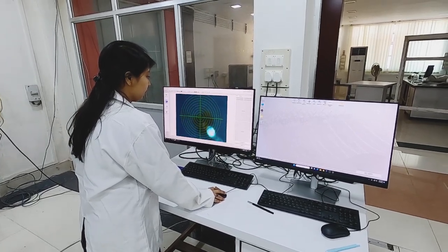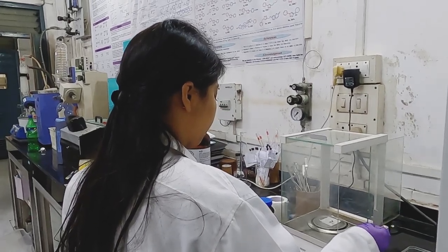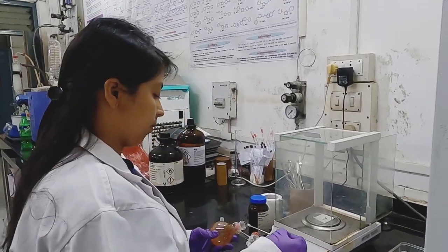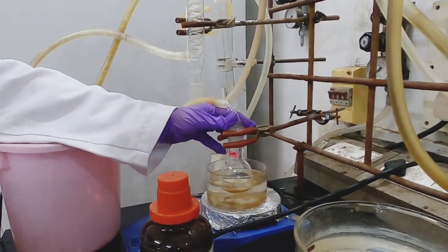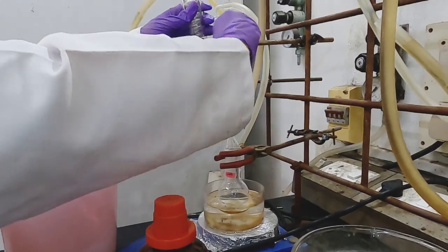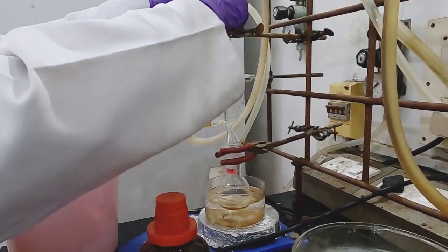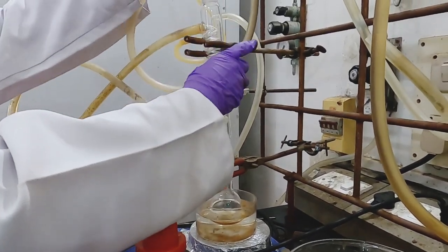The catalytic activity of this complex was further explored in the C-C cross-coupling reaction of aryl boronic acid and acetic anhydride. The oxidized version of the catalyst was also synthesized, and the catalytic activity of this complex in the C-C cross-coupling reaction showed a lower yield of the product, that is acetophenone, than the reduced catalyst.